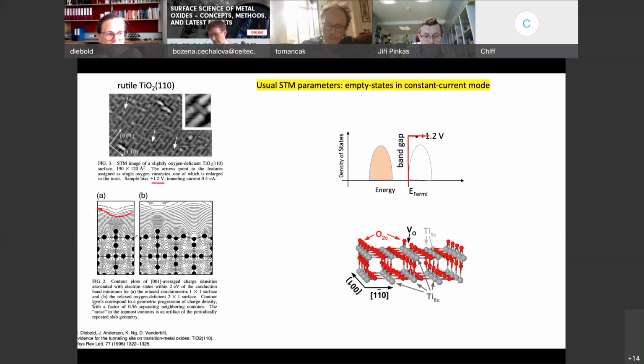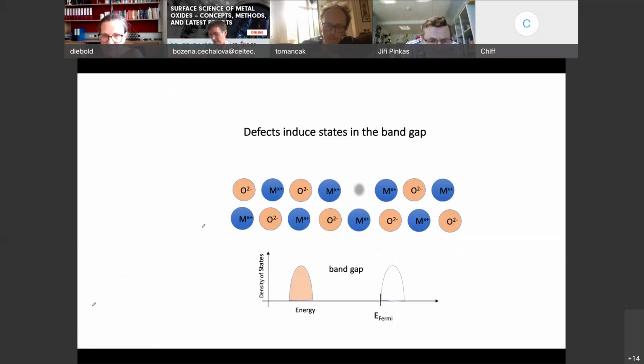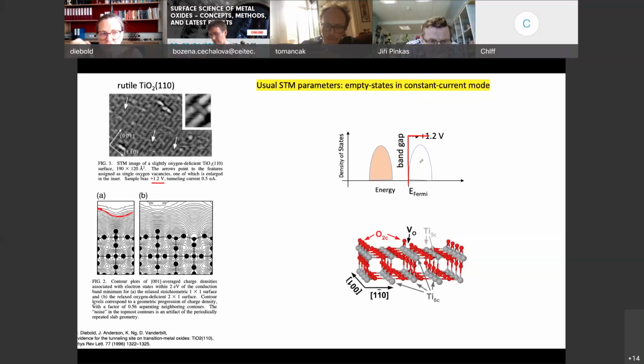Here on top of the titanium atom, there are more possibilities for the electrons to pump back in, more empty states. So here the tip moves back. It moves up and down. When it's on top of an oxygen, it moves up. When it's on top of the titanium, it moves down: up, down. And here, where there is an oxygen vacancy, these empty states are disturbed, so we have more empty states available. So here the tip moves even higher up.